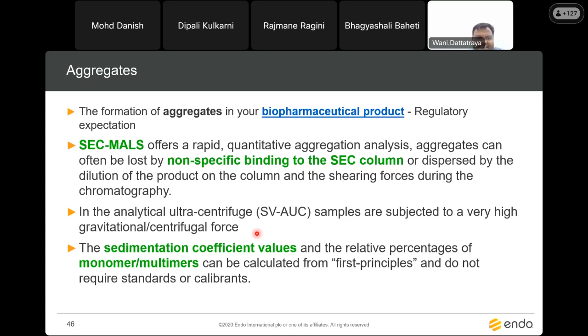One of the most important is SEC-MALS. SEC-MALS is nothing but size exclusion chromatography with a multi-angle light scattering detector. That is the most commonly used technique for the determination of aggregates in our molecule. One disadvantage of this technique is that when you are using the size exclusion column, there is a possibility that our molecule binds to the column, and that will mislead the result. Also, when you dilute the sample and load it on the column, there is a possibility that soluble aggregates dissolve, and you will get improper data. So to prove this, you have to use a complementary or orthogonal technique.